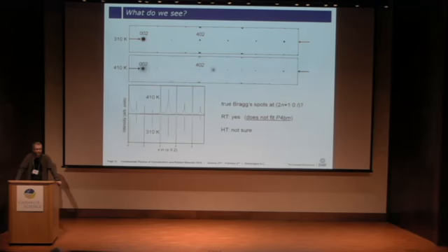And I'm not even sure that there is a Bragg component, properly speaking, in this. By the way, if you look at these Braggs at low temperature, they do not fit the P4bm space group. They don't fit it, which puts some questions on the validity of the published structure model even at room temperature.